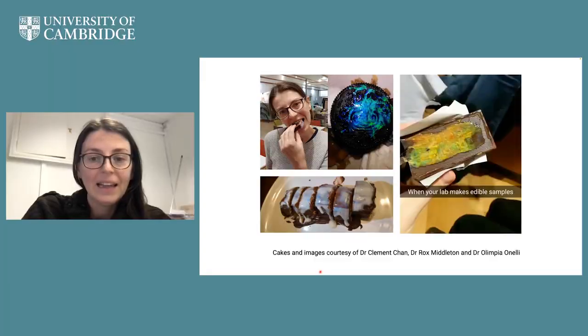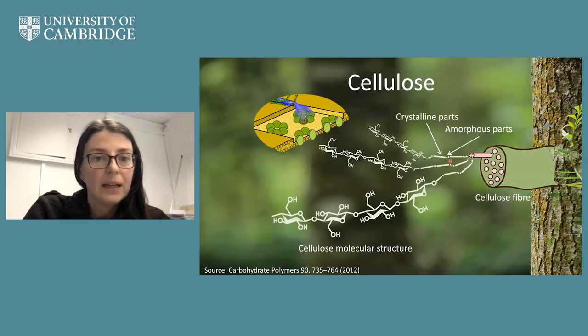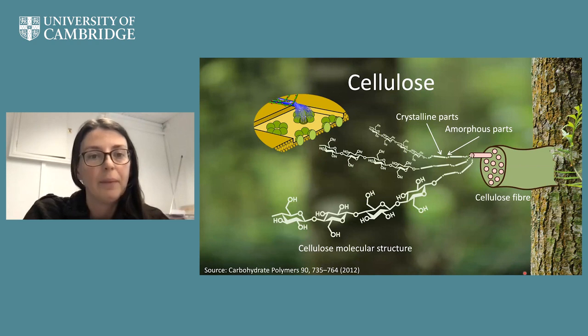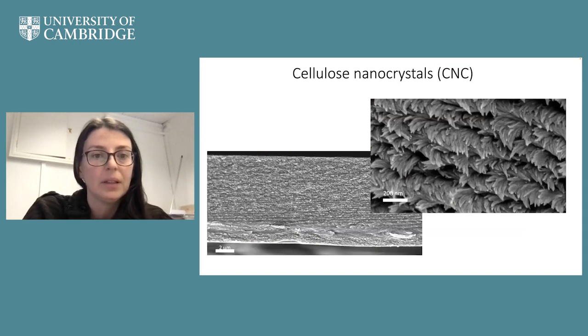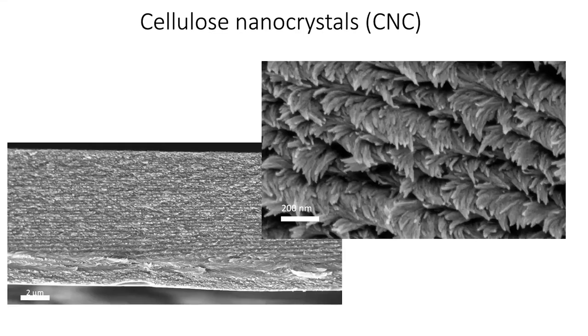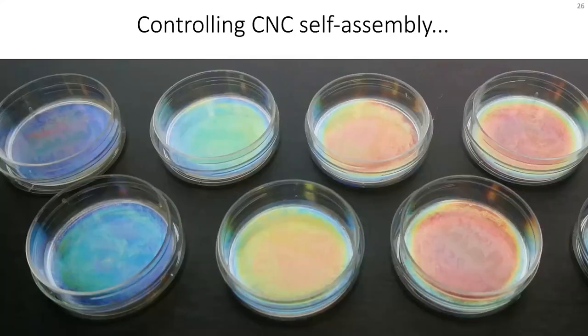Another system that we use a lot is called cellulose nanocrystals. The cellulose nanocrystals are essentially derived from the crystalline part of the cellulose fiber. So this is not a cellulose derivative where some chemical process has been performed to change the OH group of the native cellulose. Here we use only the crystalline colloidal particle itself. And what is really beautiful with this system is that the material becomes solid, so you can maintain this helicoidal architecture in the solid film, and you can make colored films made only out of pure native cellulose.